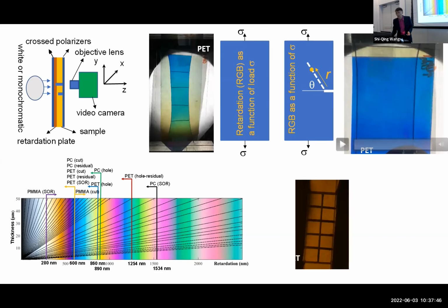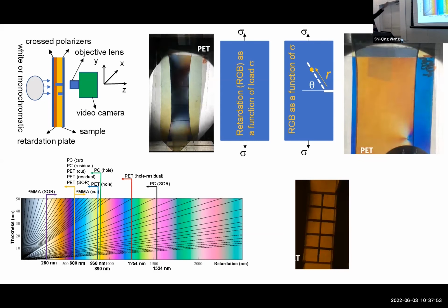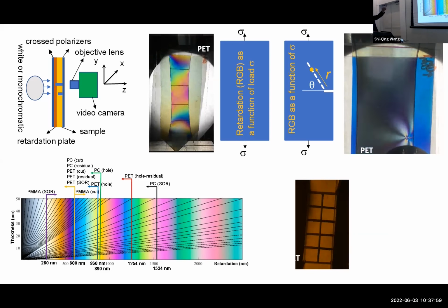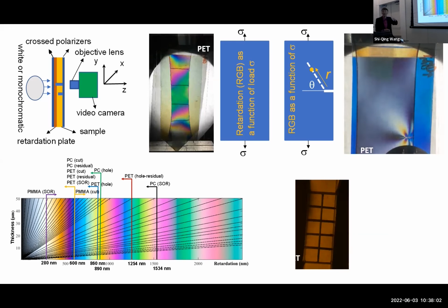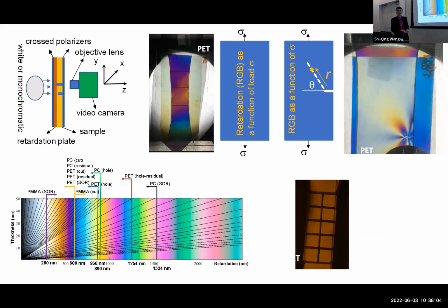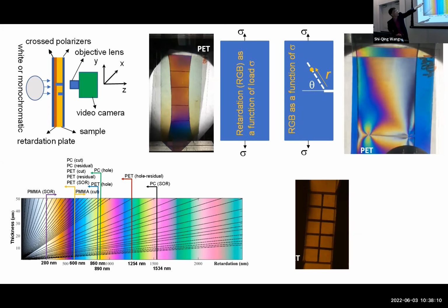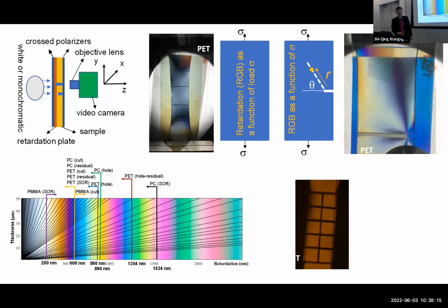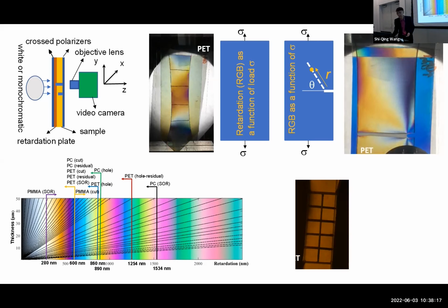of the correlation between, see, this is a white light with crossed polarizers. So I have two different samples, the other one with a cut already. So I can at least keep track of the molecular deformation that's taking place. In the case of uncut, it correlates with the stress that occurs. In the case of ductile material, you see PET on the right figure doesn't go brittle failure, it necks and yields.